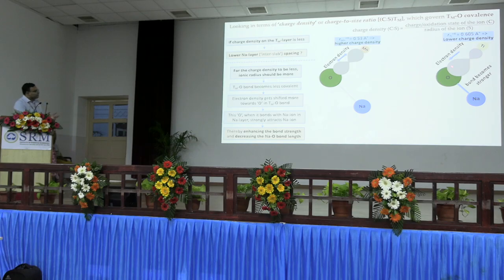Now, if we make the transition metal oxygen bond less covalent and more ionic, I will have the electron density more towards the oxygen ion, making the effective negative charge on the oxygen ion a little more negative. If I do that, then I make the sodium oxygen bond a little stronger and shorter.